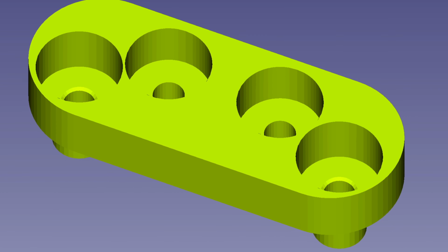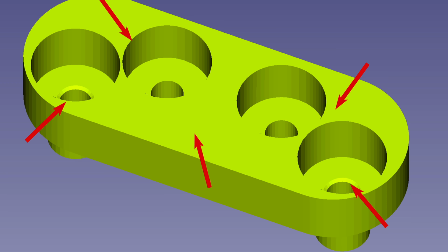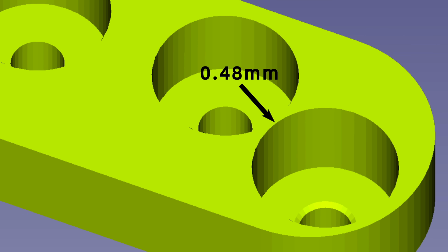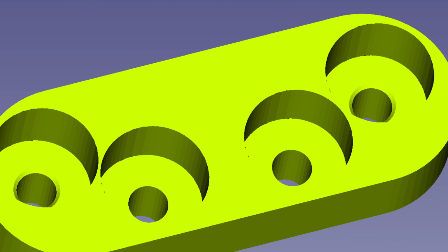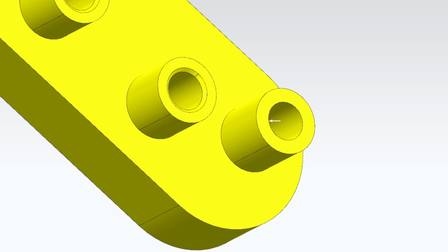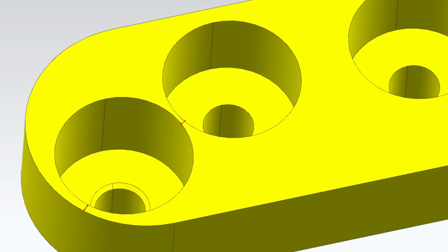From this 3D drawing, we can obviously see that the wall thickness of this component is not uniform at all. The thinnest area is even less than 0.5 mm and the thickest area is almost 12 mm. But according to our experience, the recommended wall thickness is about 1 mm to 3 mm. Let's use the wall thickness of the four bosses as the nominal wall thickness. We need to make the thin areas thicker and the thick areas thinner.